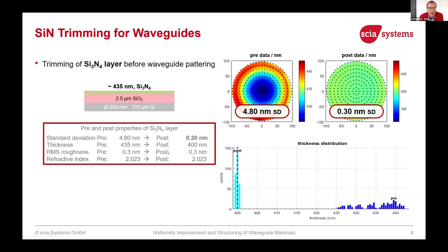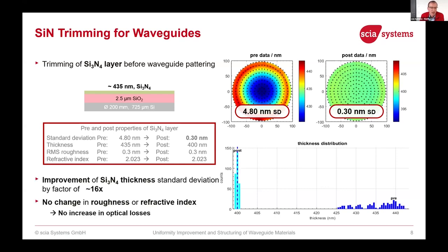So the roughness pre and post processing stayed the same, 0.3 nanometer. And also the refractive index of the silicon nitride stayed the same at 2.023. Post and pre is the same. So we achieved the improvement of the silicon nitride thickness standard deviation by a factor of 16. We did not change the roughness or the refractive index, means no increase in optical losses.